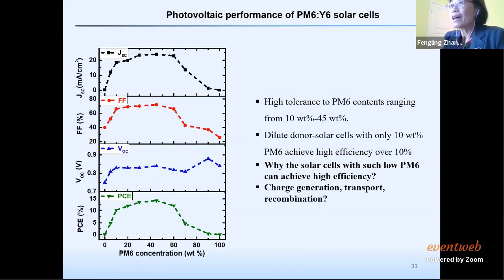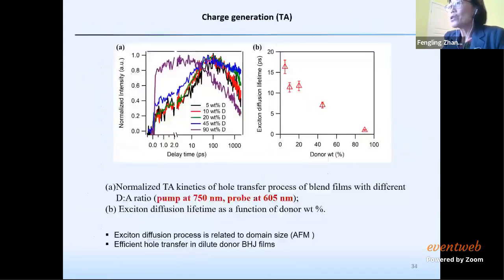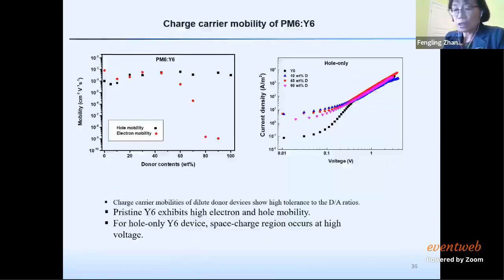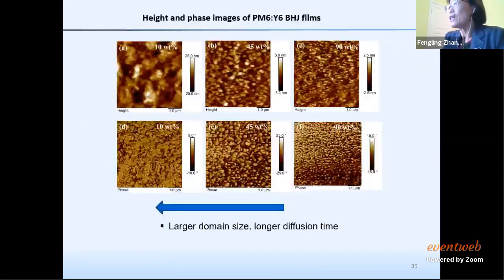We can see there's a saturation region, from 20% to 60%. They are not so sensitive to the stoichiometry. They are quite good. This transient absorption also shows, for the device with 20% and 45% optimized, quite similar behavior. Okay, so here's the morphology, which shows the domain size varied.